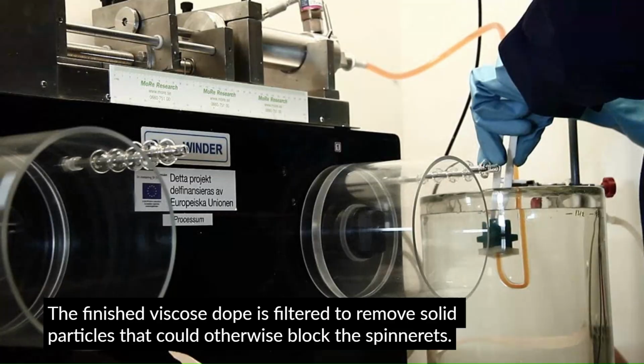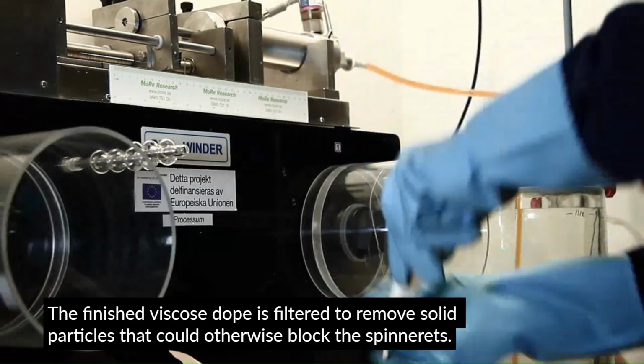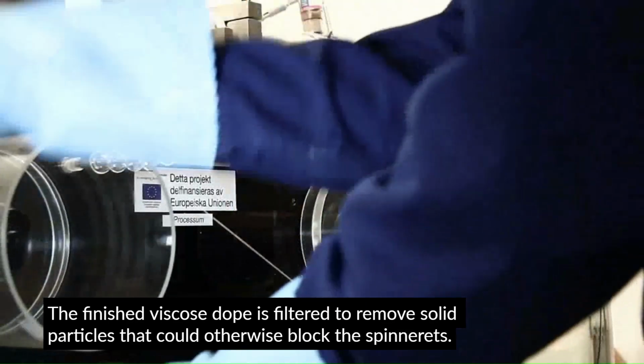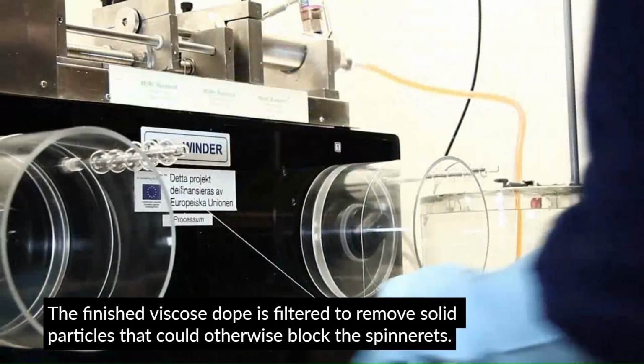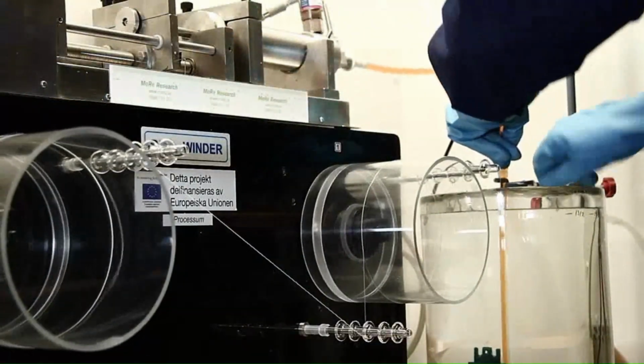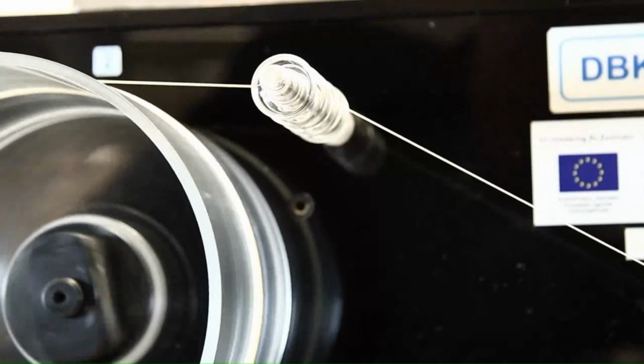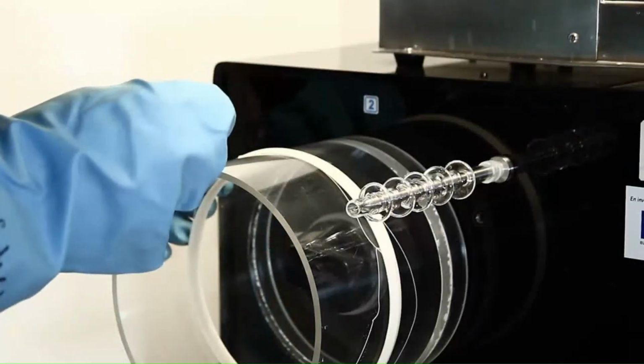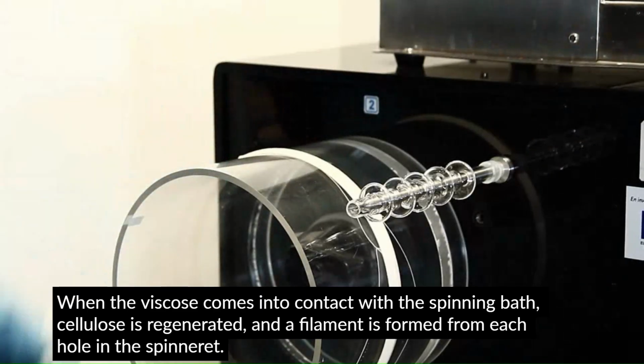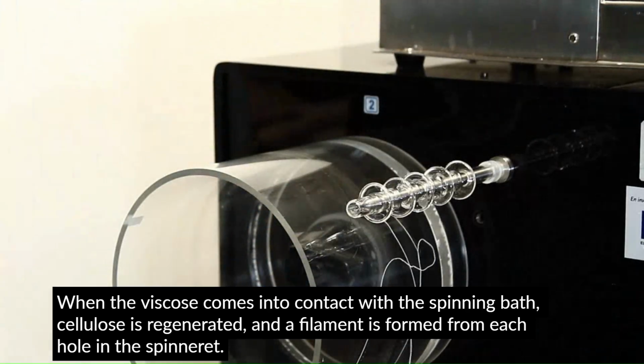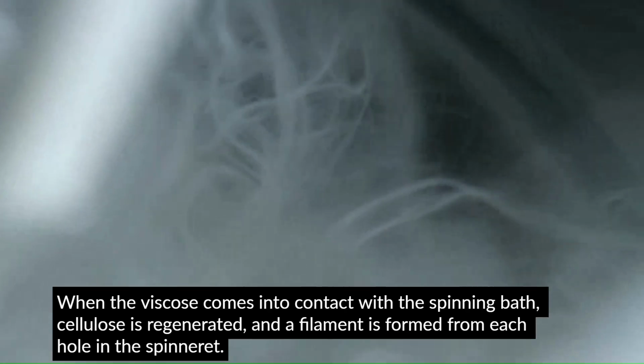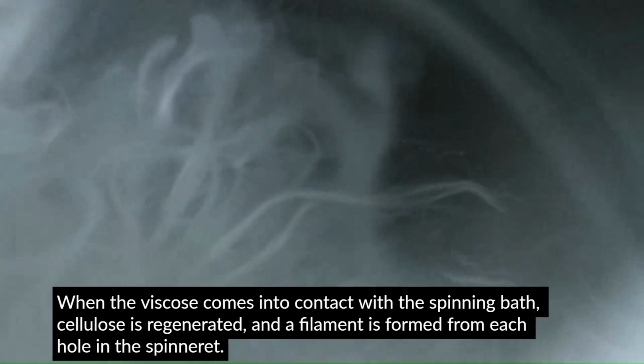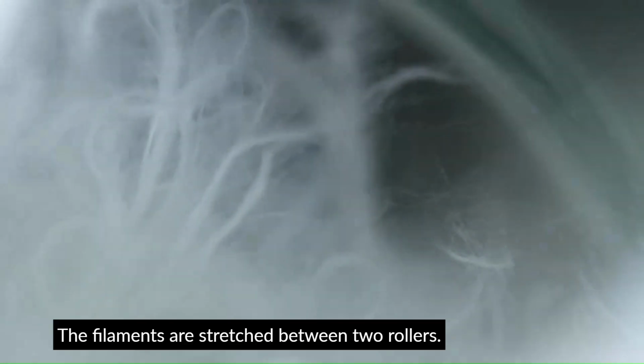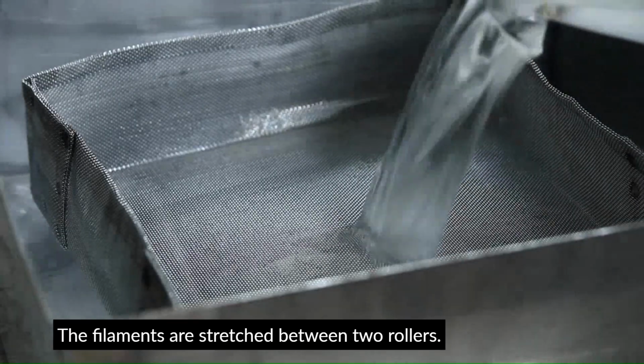The finished viscose dope is filtered to remove solid particles that could otherwise block the spinnerets. When the viscose comes into contact with the spinning bath, cellulose is regenerated and a filament is formed from each hole in the spinneret. The filaments are stretched between two rollers.